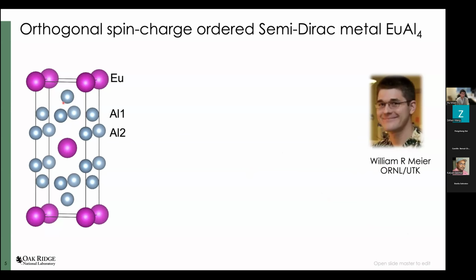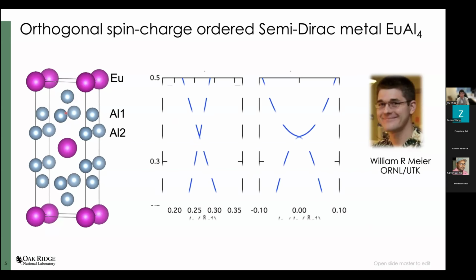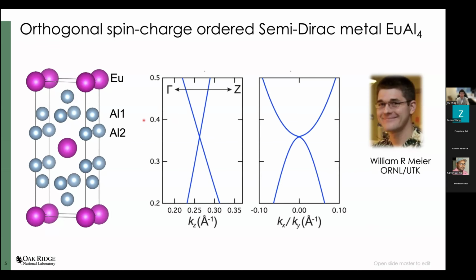Here is the crystal structure of EuAl4. The structure, I think many of you already know, is the same as the famous iron-based superconductors and heavy fermion superconductors. If you look at the band structure of this material, it's actually a semi-Dirac semimetal. When I say semi-Dirac, it means the band dispersion is linear along one direction and parabolic in the plane perpendicular to that direction. More specifically, for this material, along the kz direction shown here, it's a linear Dirac cone. But if you look at the dispersion in the ab plane, it forms a parabolic touching. So this is what I mean by semi-Dirac metal.